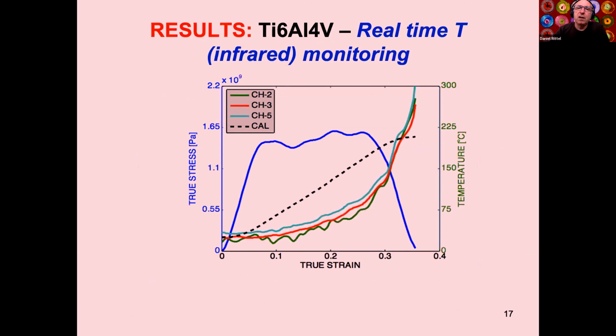So since the temperature is a key component of the story, we want to measure the temperature in real time using infrared monitoring. Infrared monitoring is based on using an infrared detector, which doesn't suffer the limitations of an infrared camera. In terms of response, you can go very fast, several mega samples per second, but you're sampling one pixel or more. So this is a bit of a delicate technique, so it's not very popular. But let me show you some typical results.